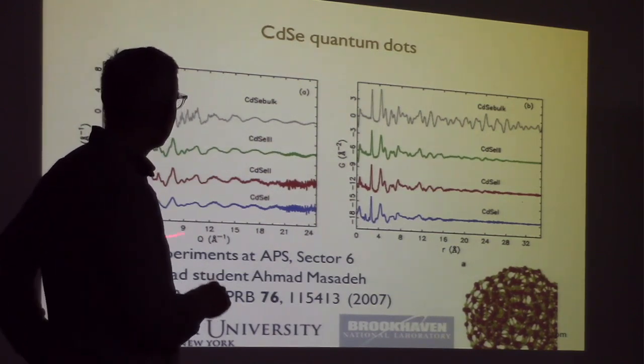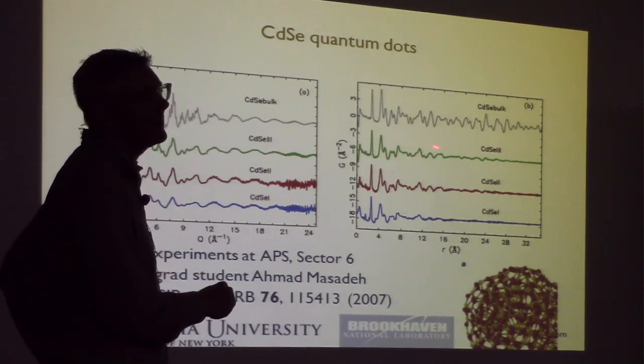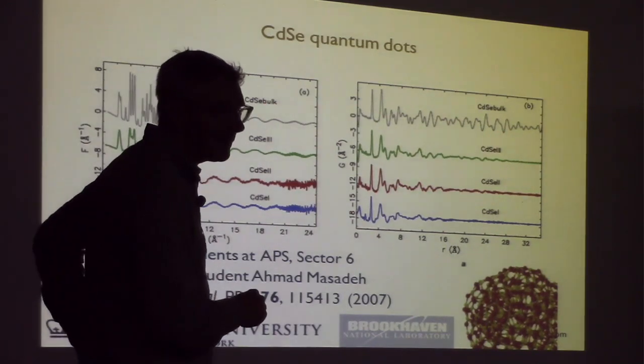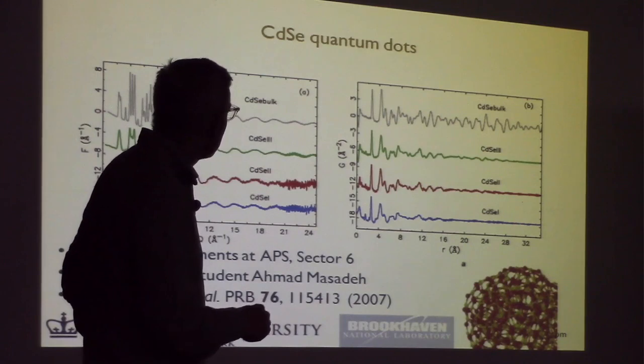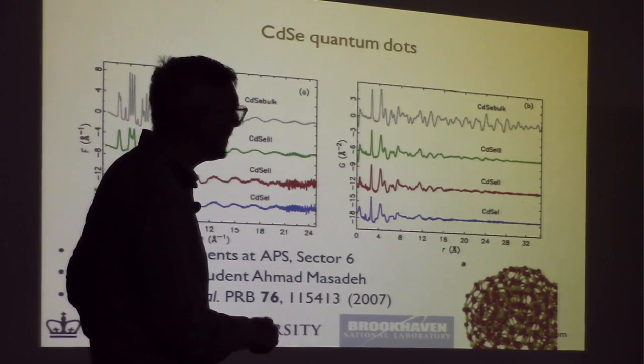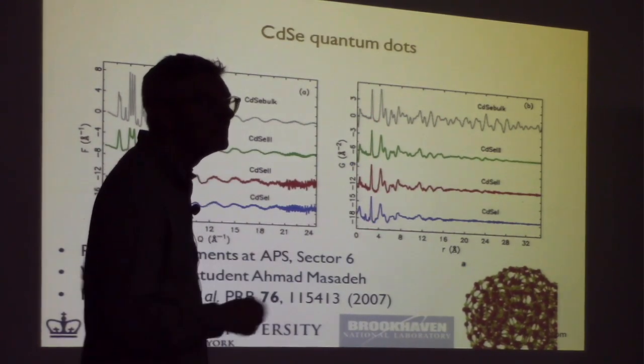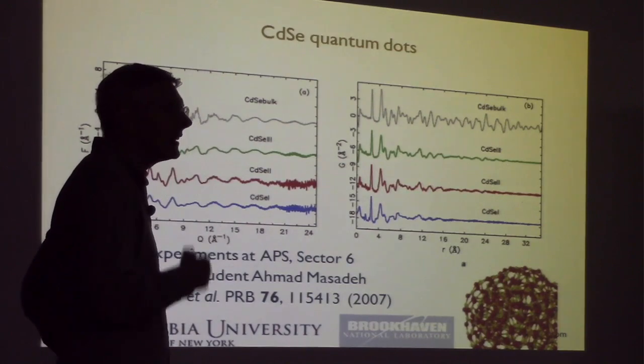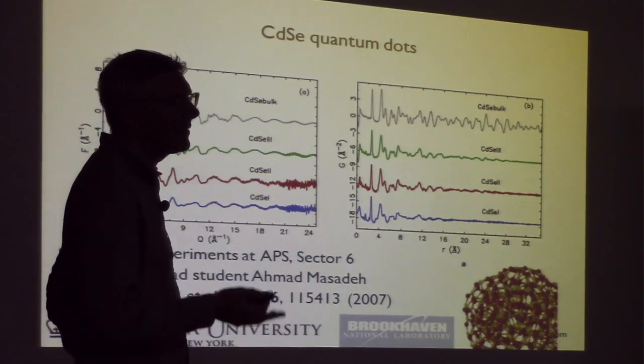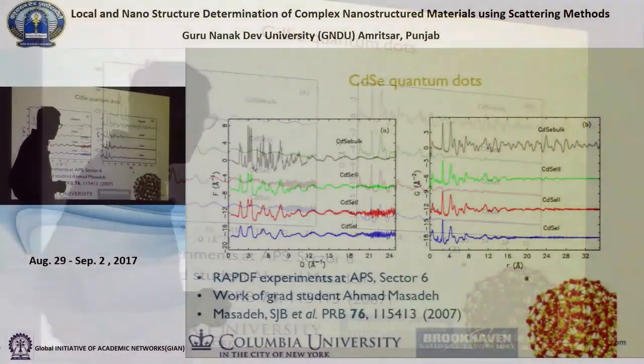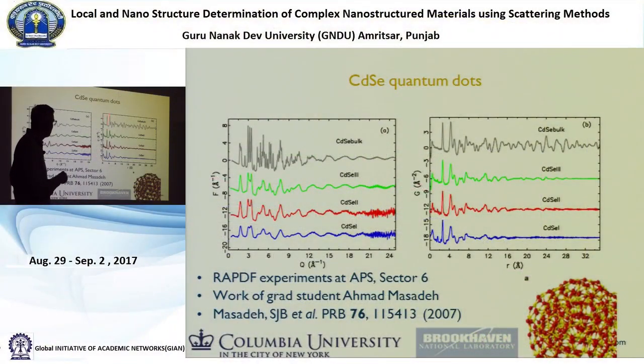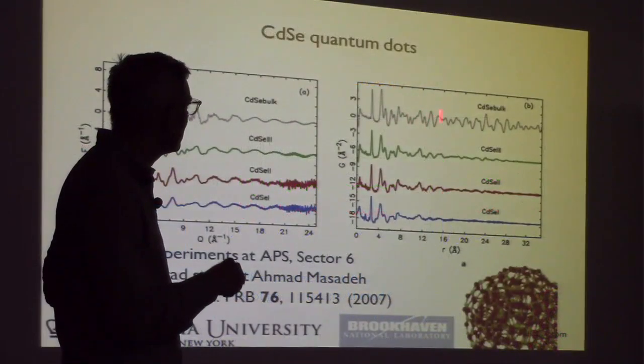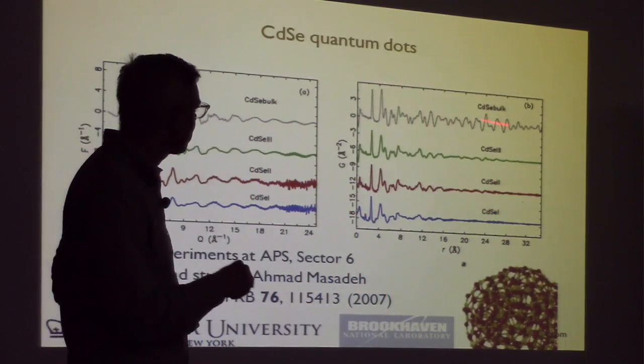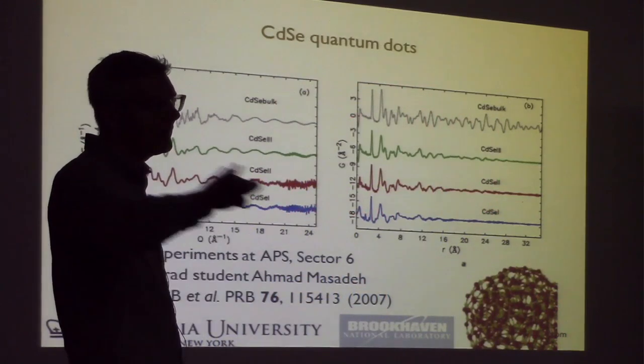So we're going to take the data, Fourier transform it to get the PDF. And we look at the PDF, and something different happens in the PDF. If you look at this first peak here, and you go down from the bulk all the way down to the nanomaterial, you see that peak stays beautifully sharp. So there's no peak broadening that happens in the PDF due to the finite size effect. But the place where you see the finite size effect is you see these ripples going out here. This is the structural signal. And for the crystalline material, it goes forever.